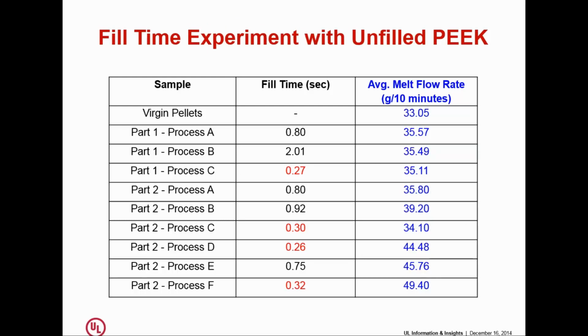So we have a lot of data here. We have two parts, first of all. One we call part 1, which was run through 3 different processes. Notice this injection speed was the one the molder wanted to use because this is what gave them full parts repeatably. And this is the one that the end user wanted them to use. They had an advanced degree guy hovering over them while they were developing the process, telling them that any shear rate that exceeded a certain value was automatically going to damage the material. And you can see that there's virtually no difference in melt flow rate between the slowest speed and the fastest speed.